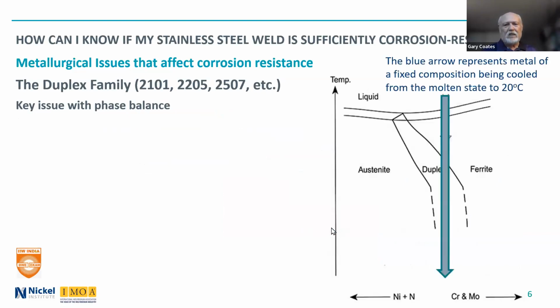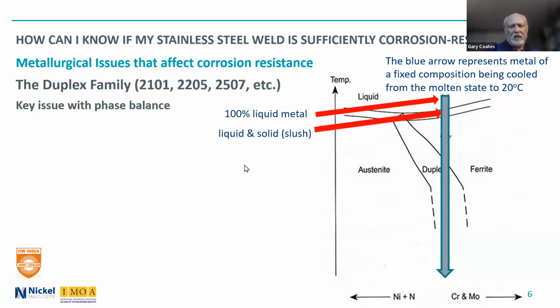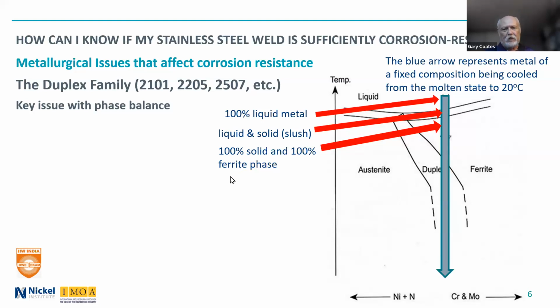So I'd like to show this, and I'll go through it very quickly, about what happens and why it's important. On the vertical axis is the temperature; you can ignore the composition. We've chosen a duplex composition here, and this blue arrow is as it goes from liquid through to solid and then all the way down through temperature. Up at the top, it's 100% liquid metal, and then we have liquid and solid forming. I call it slush. Those of you who know snow, you have been in slushy conditions. And then it becomes 100% solid. And when it becomes 100% solid, it is 100% ferrite phase.